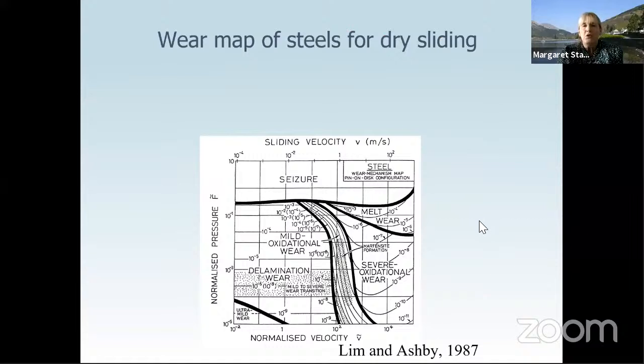And these are various regimes associated with the sliding wear phenomena of two metals on the surface, resulting in oxidation on the surface, oxidational wear here, which is not very beneficial, but quite beneficial here is severe oxidational wear, where we get the formation of a so-called glaze layer on the surface, which reduces wear.